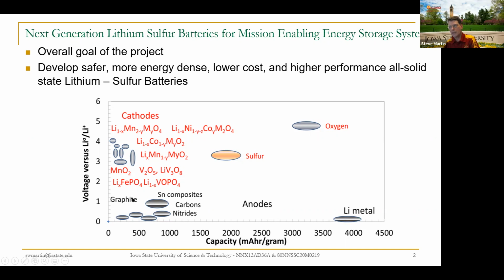And of course, in those applications, you're always interested in increasing the energy density. The lithium-ion batteries that all of us depend upon every day in our cell phones, even automobiles, are the graphite transition metal oxide batteries. And graphite stores the lithium relatively safely on the anode. And the transition metal then, of course, is the redox couple. Depending upon which particular transition metal you use, most of us now have shifted over to the nickel manganese cobalt system to reduce the amount of cobalt. When they were first invented 30 years ago, lithium-ion batteries were pure cobalt, and that's way up here around 4 volts. We suffer a little bit lower voltage by going to the manganese nickel couple, but you reduce the cost dramatically by getting the cobalt out.